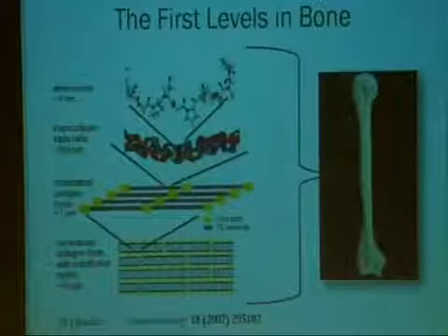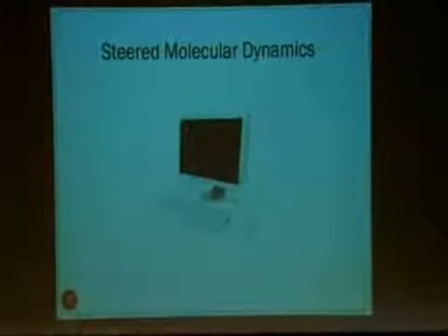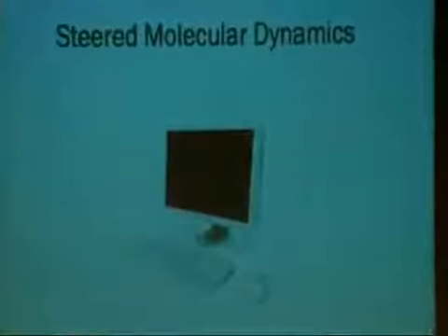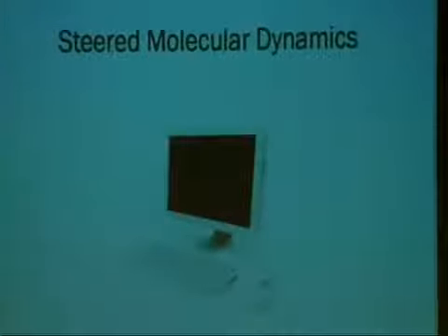So in this study, I wanted to examine the interactions between the collagen and the hydroxyapatite, and basically understand what happens when collagen is sheared across the surface of a nanocrystal of hydroxyapatite, and decide whether it depends on the size itself of the crystal. So to do this experiment, I used steered molecular dynamics simulation, which is a great computational method that enables us to predict the behavior of a system when it is under load, meaning that we combine both experimental data that is already known to us as well as theoretical calculations.